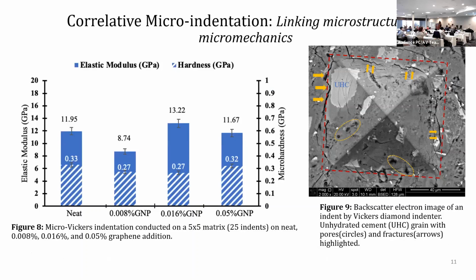We did some indentation to look at how the material behaves at the micro scale, so that we can relate that to single phases from the previous images that I've shown. The downside of indentation is that you're not having the sample in confinement. So the elastic modulus and hardness that we obtain from these measurements are more of an indicator of whether this is substantially different or not. But that is not the kind of test that I would rely on completely to decide whether graphene is qualified to be used in the field. That test is coming later. But you can see that 0.008% did contribute to reducing the Young's modulus.